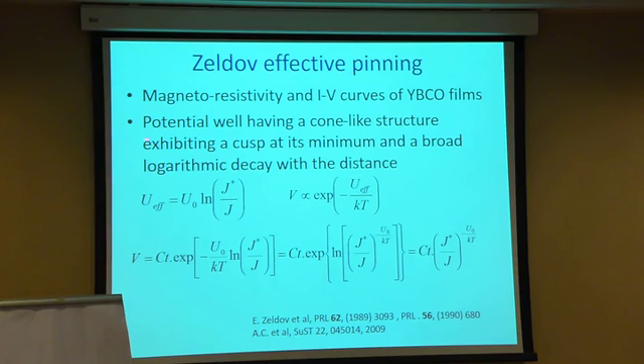And what does it say? So these are experiments from which Eli Zeldov got these types of dependencies. What he says is that in YBCO films, the potential will have a cone-like structure very close to the pinning, and after that it goes exponentially. So it has a totally different shape than the square potential well in the Kim-Anderson model. So what he says is the effective pinning potential depends logarithmically on the current.